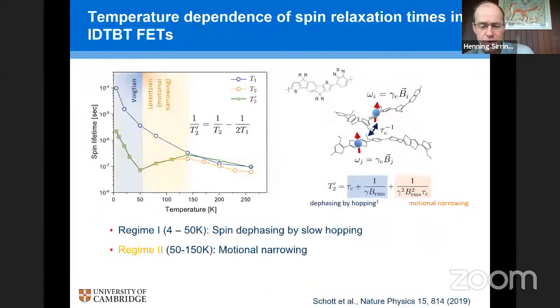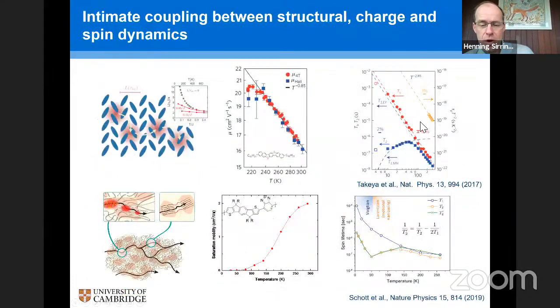This last result that I showed, they were both field-induced ESR measurements, not done by us. The top result is for a molecular system investigated by Jun Takeya's group in Tokyo, but it's a field-induced ESR measurement, essentially the same experiment that we have done for the polymeric systems. So they are more or less directly comparable, and they show very similar behavior, which is something that surprised me, because I hadn't expected that systems that supposedly have such different physics end up having spin relaxation times that are very similar. They're both around 100 nanoseconds at room temperature, and have also very similar temperature dependence.